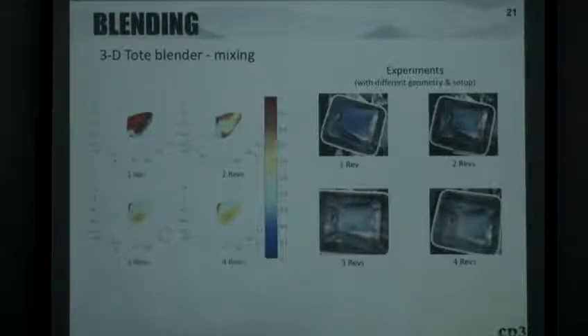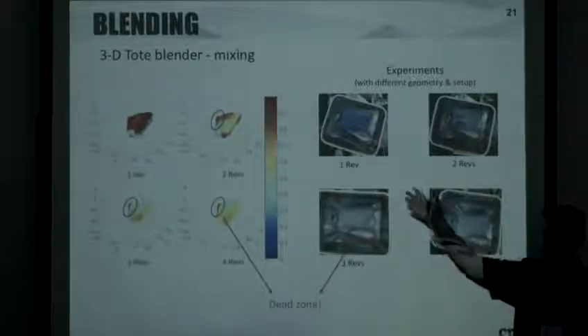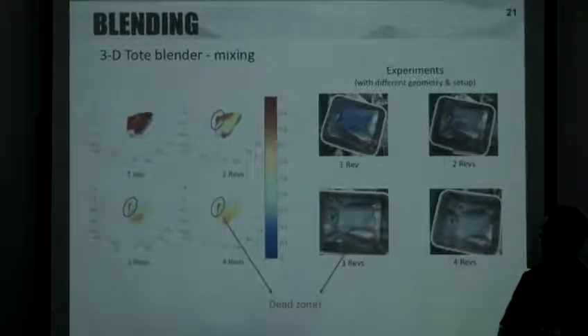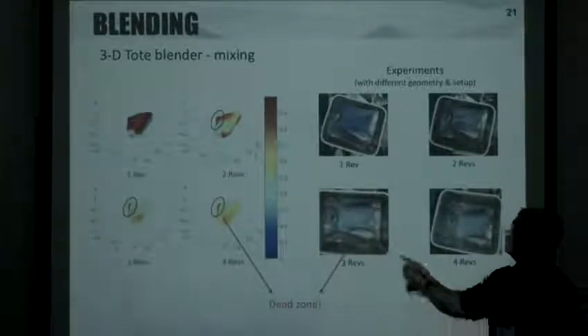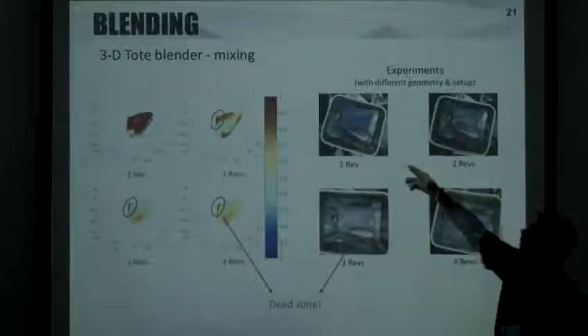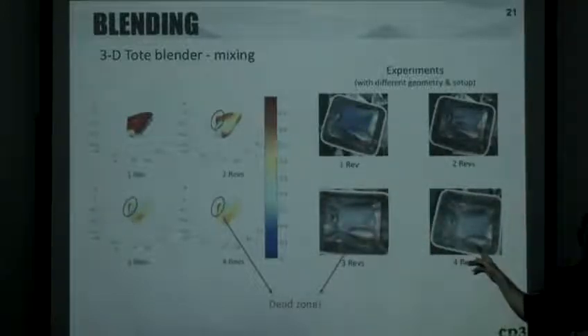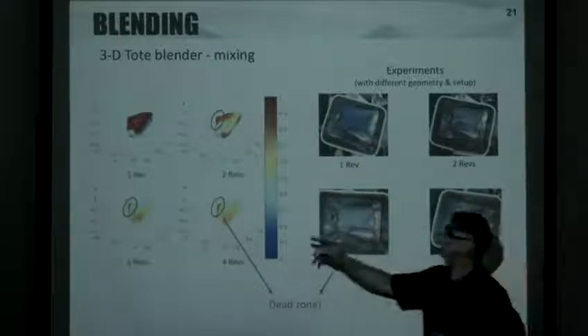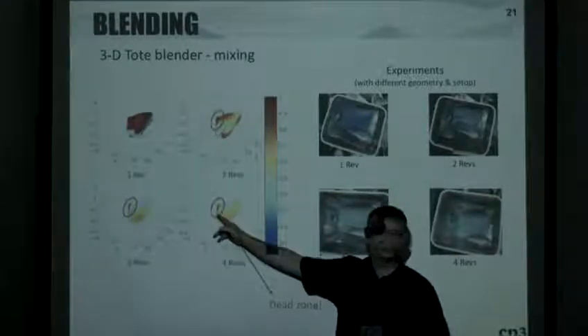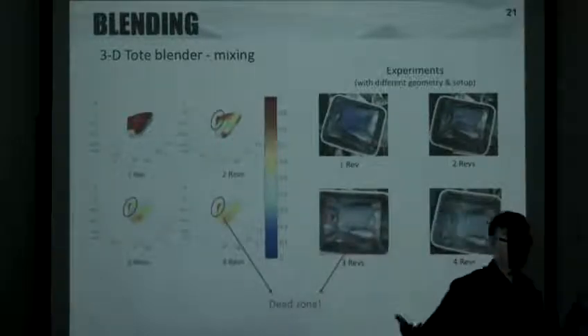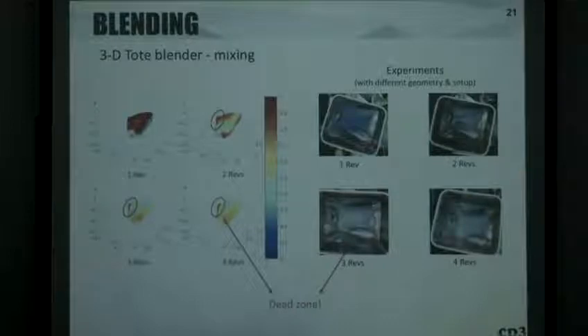Another interesting thing is that we actually did some experiments of our own to try to measure the mixing. We had trouble with it because every time we rotated a couple of revolutions, we'd use a thief probe to sample so we could get a mixing index. But every time we used the thief probe, we disturbed the powder beds so much that it became impractical. But when we ran those experiments, we had blue and white spheres, and we noticed there was a dead zone where things didn't mix. And interestingly, in the simulations, we saw a dead zone there as well. So qualitatively, it produced some similar results.